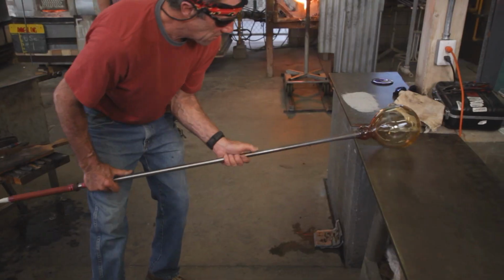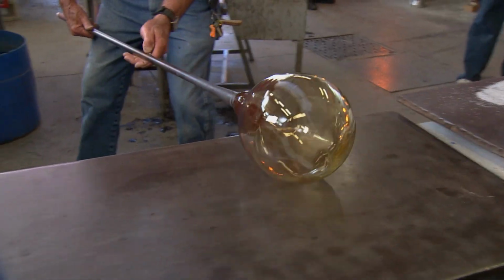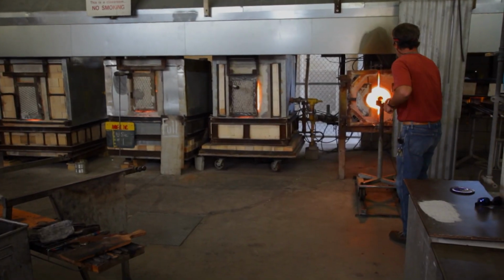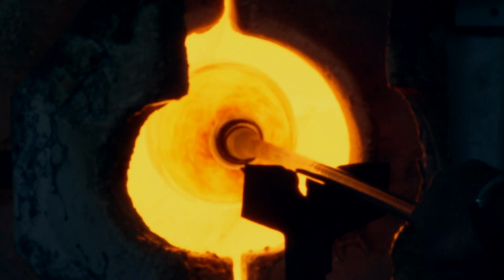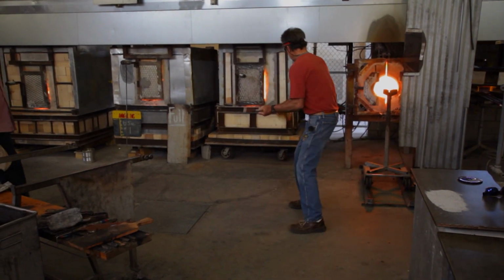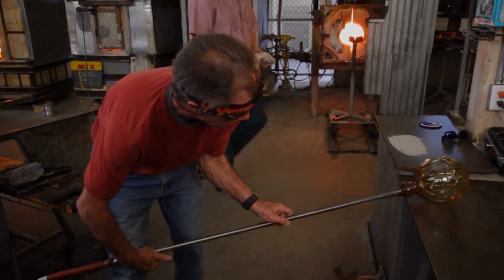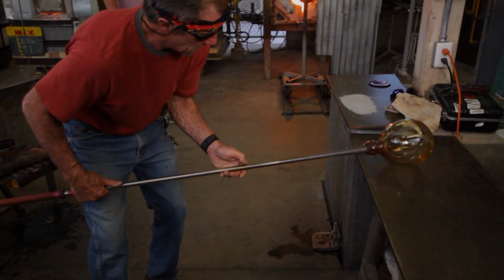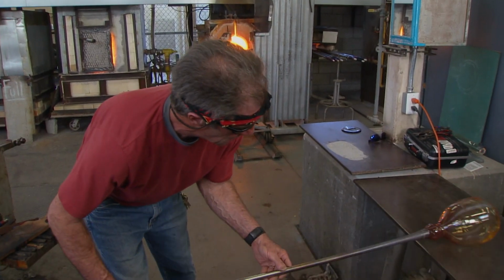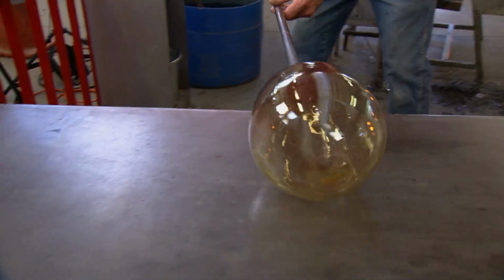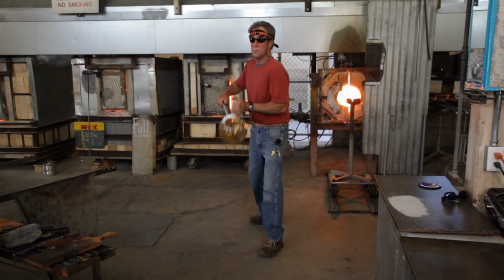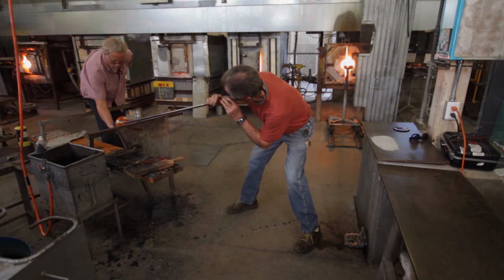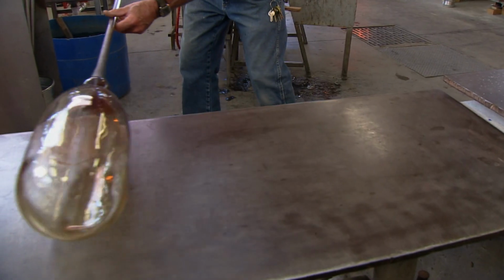So then you do your gather, and then what? How do you get that long cylindrical shape? Well, how I do it is I first start by blowing a round bubble, and that is going to be wider than the diameter of the cylinder that I'm going to try to finish. Then I heat it up to where it's fairly loose, and what I mean by loose, it's actually moving at the pipe. Then I let gravity sort of elongate the bubble to where it gets almost the diameter that I need it for the cylinder. And then what I do is I take a series of rolls over a table like this called a Marver table and establish the diameter of the cylinder. Once the top part of the cylinder is established, I can continue to blow wider and swing down and Marver to that diameter. So it's puff, establish your diameter, puff wide, swing down, establish the diameter, puff wide, swing down, establish the diameter. That's essentially quite a long process.